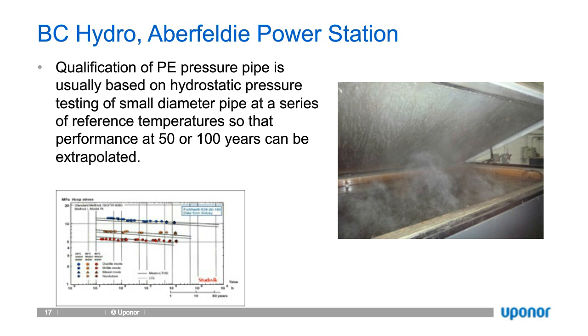On the right image on the slide is an elevated tank. Typically, all of this testing has to be done at controlled temperatures, and that's done by putting the samples of pipe in a tank. In this case, this is one of the elevated tanks where the water is at 80 degrees C. And in a tank like this, one can easily put 50 to 100 samples of small diameter tubing. So to determine the stress rating of PE solid pipes, they are pressurized at known wall stresses and left pressurized until failure occurs at a significant number of stress levels. What you're seeing on the little graph, each one of those dots is a failure point. Stress level on the vertical axis and on the horizontal axis, the duration at which the ductile failure occurred.